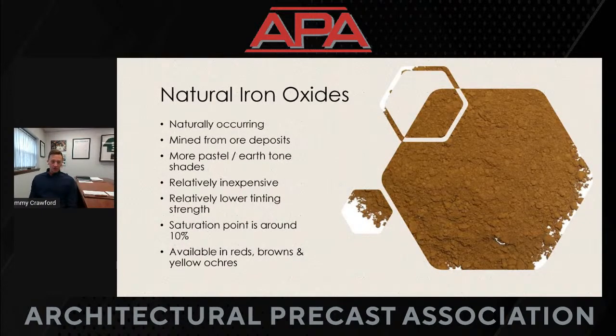Natural iron oxides. So this is the other category that iron oxide pigments can fall into. These are naturally occurring minerals in the earth. They are dug up, they are mined from iron ore deposits, and then ground into powder. As you can see on the right-hand side is what we would call our number 25 dark buff. It's the most common selling pigment that we have. Relative to synthetics, they are relatively inexpensive. They are said to have lower tinting strength, which is not necessarily a good or a bad thing. Typically what that means is that you would add a little bit more to achieve a more intense color. But if color intensity is what you're looking for, typically synthetics are more effective and efficient at reaching that.